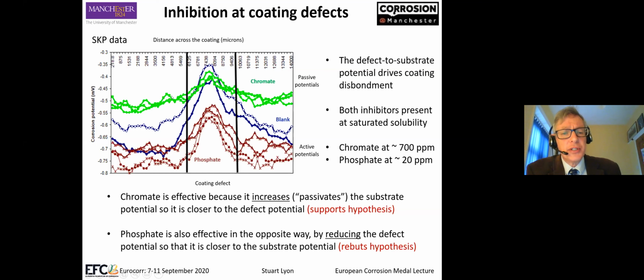And what we found was that the chromate, in essence, didn't do anything to the exposed potential, but it raised the potential of the substrate underneath the paint. So if you imagine that the potential difference between the defect potential and the substrate potential drives the coating disbondment process, then that's how chromate works. In the absence of chromate, we have this big potential here, from here to here in the blue line. The presence of chromate is much, much less. The driving potential for coating disbondment is much less.